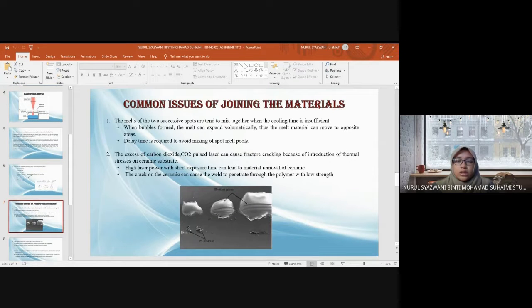Here are the common issues of joining the materials using this kind of method. First, the melts of the two successive spots tend to mix together when the cooling time is insufficient. So bubbles will form and the melt can expand volumetrically. So the melt material can move to the opposite areas. So we need a delay time to avoid the mixing of spot melt pools.